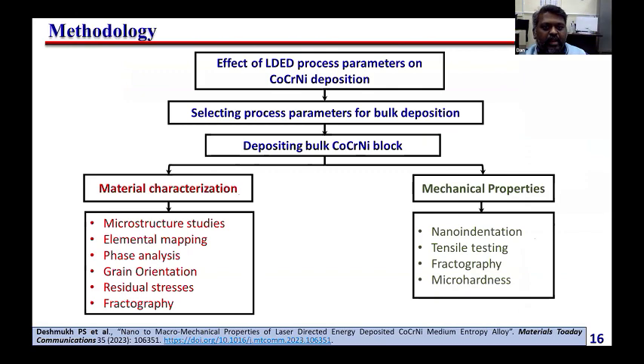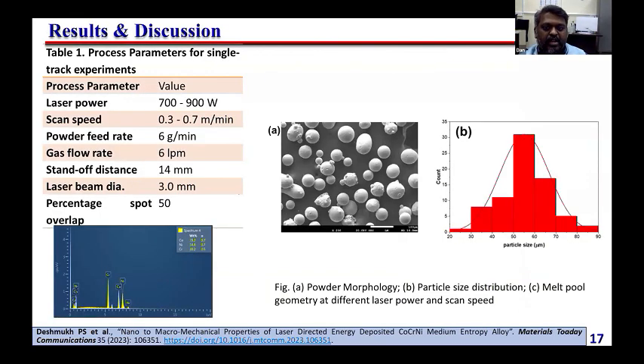Now I am coming to how we did the deposition. Initially we pre-mixed the powders. We have taken cobalt, chromium and nickel, these three powders, and you can see that they are in spherical shape. We have taken them in a near equiatomic proportion, all around 33 percent. You can see that all the powders are almost around 50 micrometer, something like this.